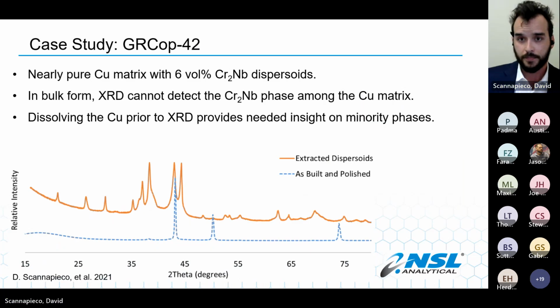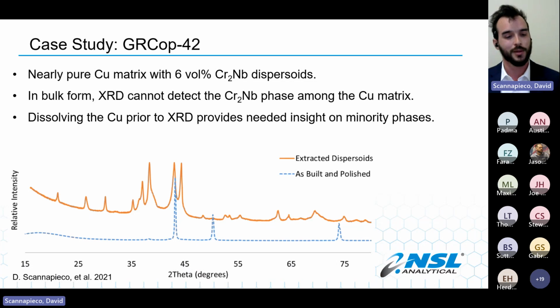So one thing that we did in my research, which again is GRCOP, this time we're working with 4 atomic percent chrome, 2 atomic percent niobium. If you conduct XRD on the bulk material, which is this blue dashed line on the bottom here, you only see the copper peaks. There's not quite enough chrome and niobium dispersoids to identify using just XRD alone. But if we take some nitric acid, dissolve out the copper, and all you're left with is the untouched chrome and niobium dispersoids, and then you can XRD that as a powder, you're looking at far more detail.